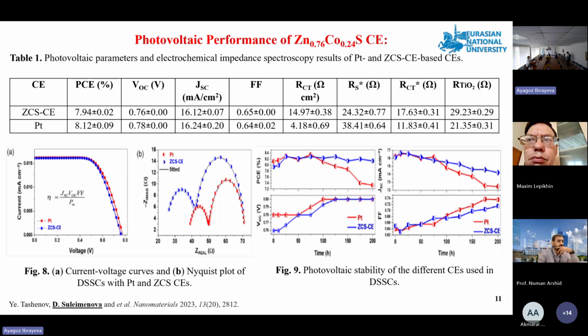EIS results indicate that zinc cobalt sulfide has higher charge transfer resistance than platinum, indicating lower catalytic activity, consistent with earlier measurements. Photovoltaic performance was monitored over 200 hours. Zinc cobalt sulfide shows better stability than platinum. VOC remained nearly constant, while JSC gradually decreases for both devices. The efficiency of the platinum-based DSSC dropped after 100 hours due to degradation in the electrolyte. In contrast, the zinc cobalt sulfide-based device remained stable, decreasing only slightly.